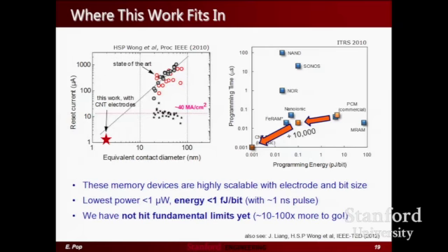To put this in context, this is what the data from industry was. This is actually a study summarized by Professor Philip Wong here at Stanford. And this is where our data is, both in terms of size and in terms of power. So we were actually able to bring down power and size at the same time, because they're actually related through the thermal behavior of these bits. So we took something that is basically a nearly commercial technology, scaled it to somewhere here on this arrow, and now we're pushing it towards femtojoule, maybe less than femtojoule operating conditions.